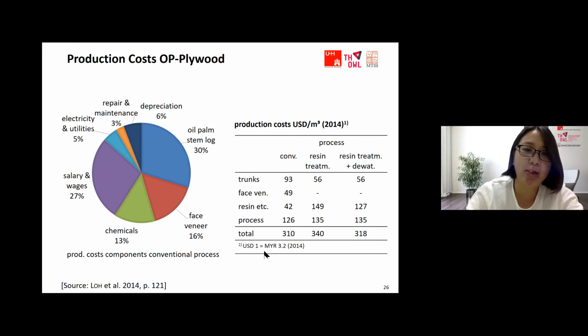The production cost shown in the table: normal OP plywood is about $310 per cubic meter. And with resin treatment, the cost will be higher due to the chemical cost, roughly an increase of about 10% to the production cost, but the cost can be reduced when we do some modification on the dewatering process. And also we can make some savings on the drying process. Okay, on the next slide.